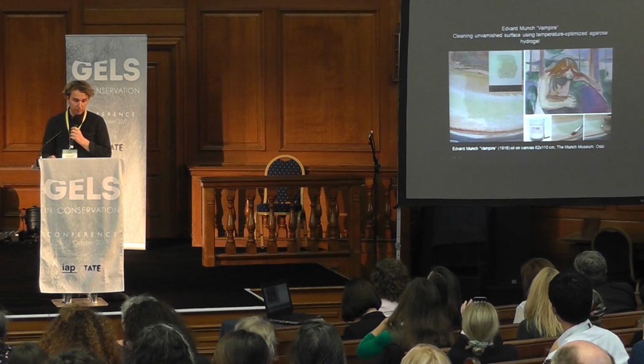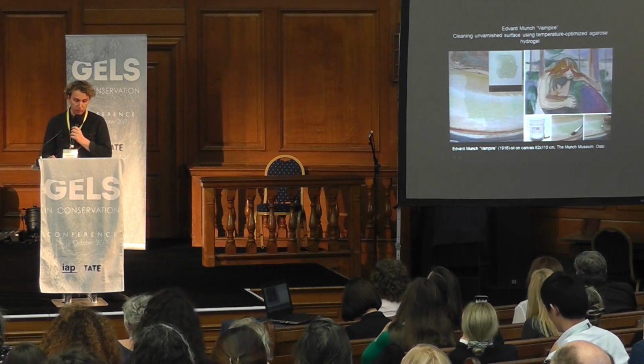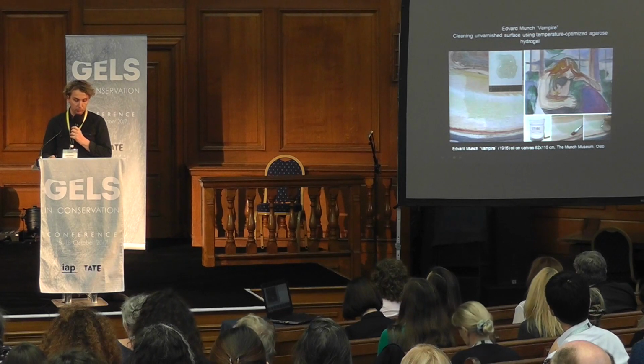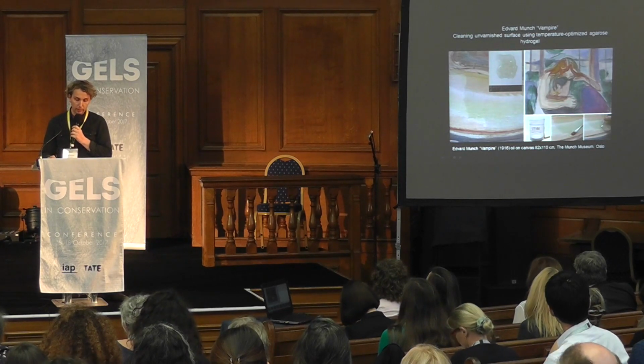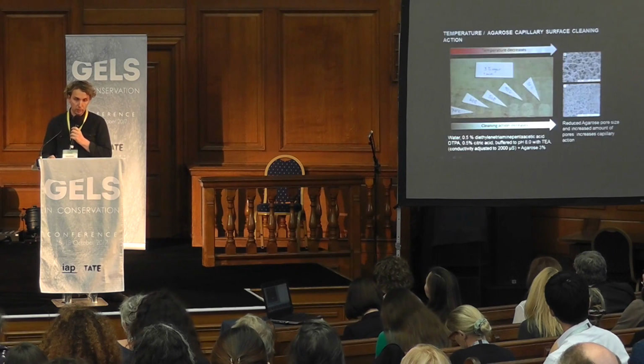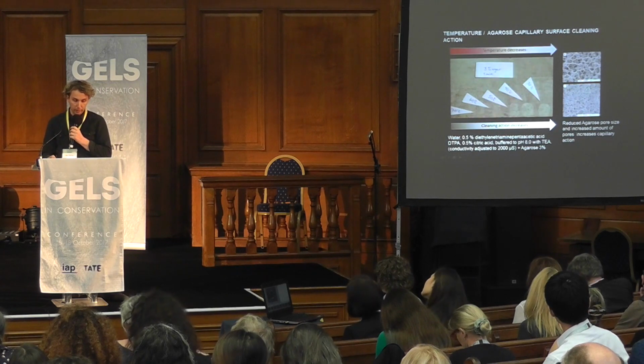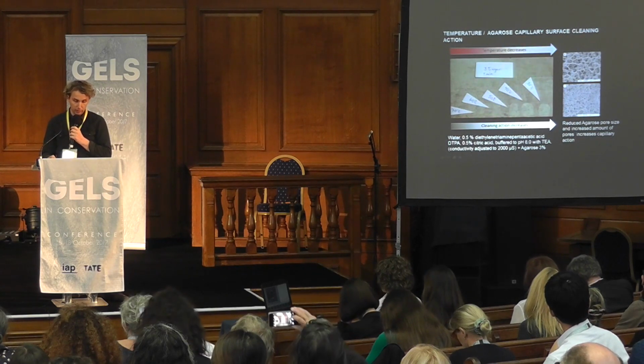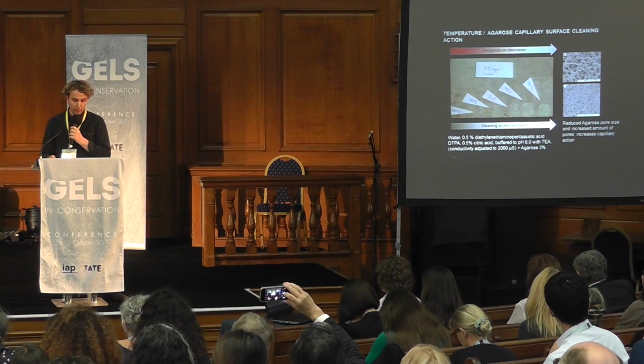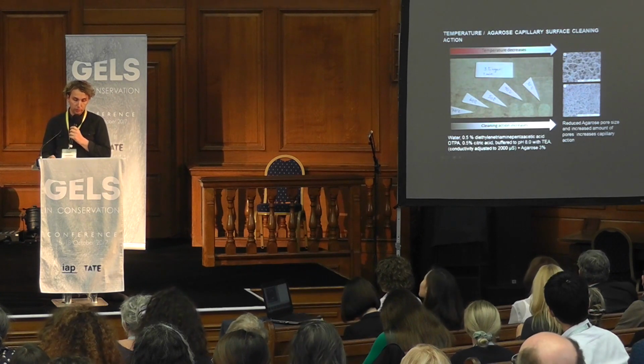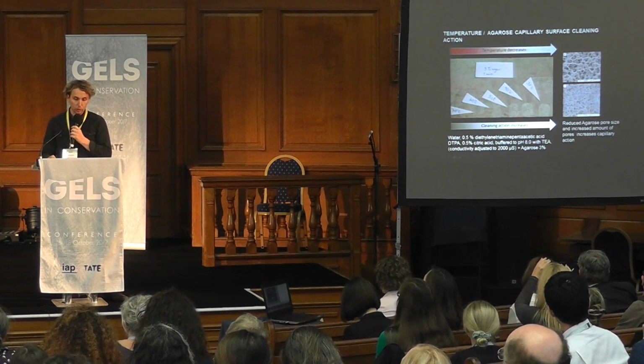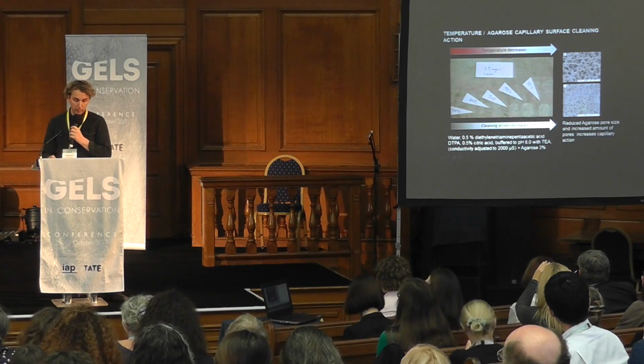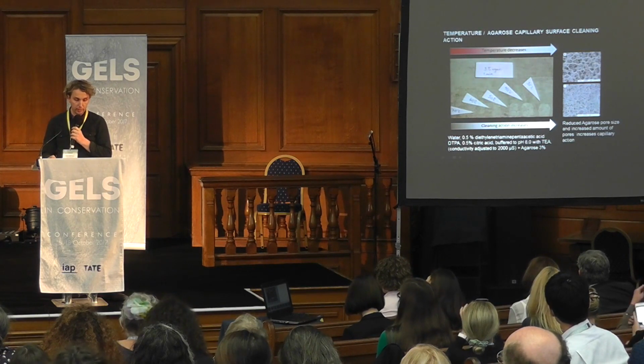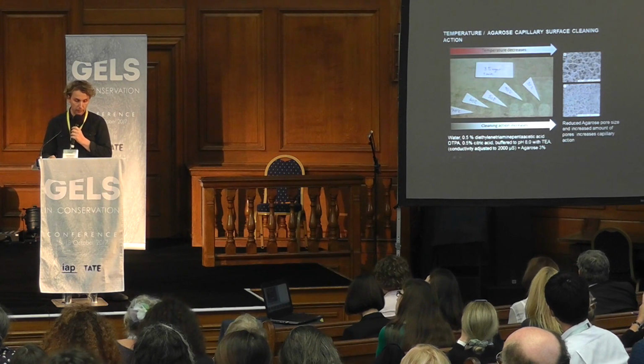To develop a safe cleaning method, we experimented with warmed agarose hydrogel applied by brush that also absorbed the soiling by capillary action and captured it within the solidified hydrogel. Prior to treatment, we tested warm agar on naturally aged and soiled canvas from the 1940s at 70, 50, 40, and 35 Celsius for 1 minute. Counterintuitively, the cleaning action in this case was stronger at lower temperature, perhaps explained by the reduction of the agarose pore size at lower temperature that increased the capillary action.